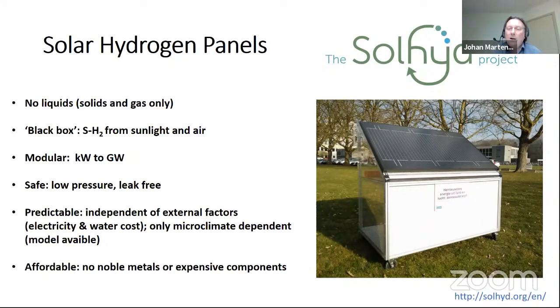So it's safe because the hydrogen that is produced is at low pressure, slightly above atmospheric pressure, leak-free, predictable, because it's independent of external factors. You don't need an electricity supply. You don't need a fresh water supply. So it's only microclimate dependent. And so we have models that simulate the functioning of the panel, the production of the hydrogen that goes up and down, up and down, up and down, a bit like a PV panel, but even more pronounced, because weather and especially microclimate, it changes quite significantly, especially in a country like Belgium. So affordable, as I mentioned already, no noble metals, no expensive compounds.